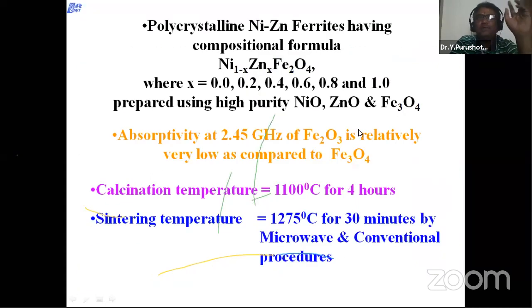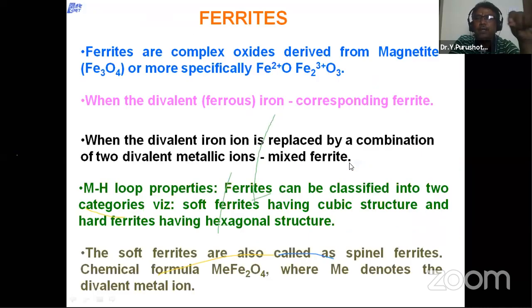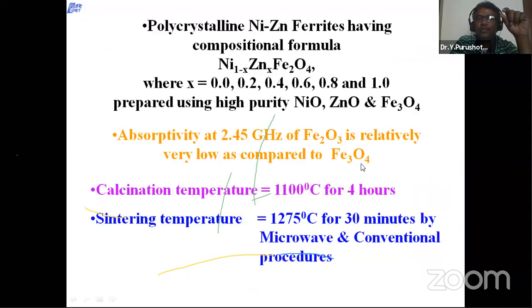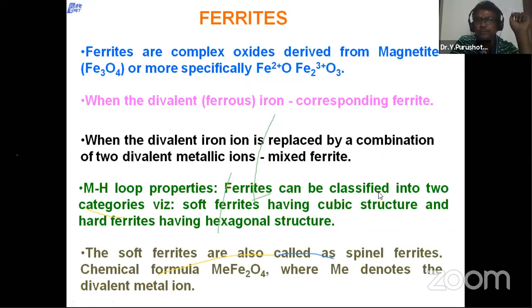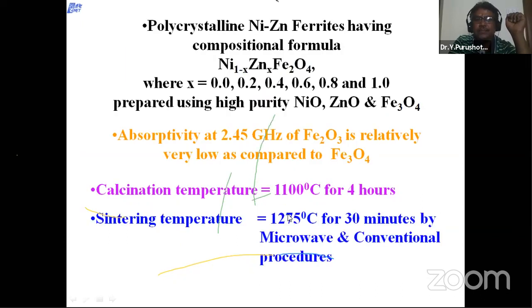So that's why we used two types of iron oxide here, and we found that at 2.45 gigahertz, Fe2O3 absorbs fewer microwaves compared to Fe3O4. So this is what we found. One has to use iron oxide as Fe3O4, and after pressing the pellets, they were calcined at 1100 degrees centigrade for 4 hours in a conventional furnace. This is not microwave. Then one batch of pellets we sintered at 1275 for 30 minutes, and in the same way another batch by conventional procedures for comparison purposes.